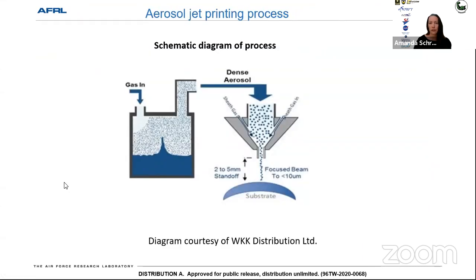And we've recently moved on to the aerosol jet printing. We have an IDS printhead in our nScrypt. And the reason for this is that we can get a very focused beam of material, but we can have a greater standoff distance so that we're not so sensitive to the ceramic tip potentially hitting the surface and cracking or causing other issues. So this is installed in our system. In the future, we will plan to add one of these to a 5-axis robotic arm. So I have some future slides, but one thing about the aerosol jet I'll just mention is that it's a very thin layer of materials. So we're still looking for, going back to those testing and designs, how to measure that appropriately for conductivity and other adhesion measurements with such a thin layer. How many layers should we make? You know, what's optimal thickness and things like that.